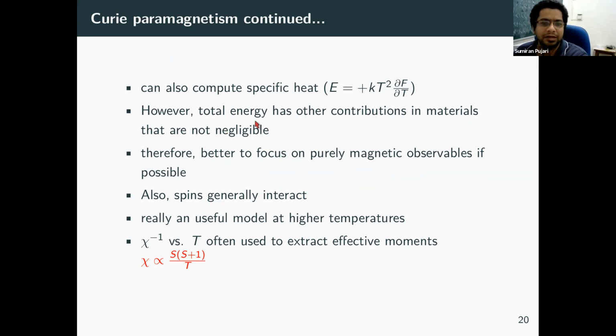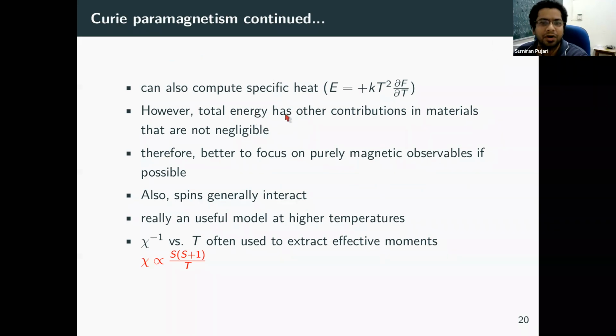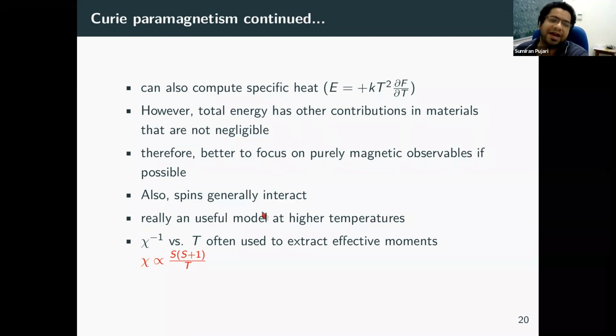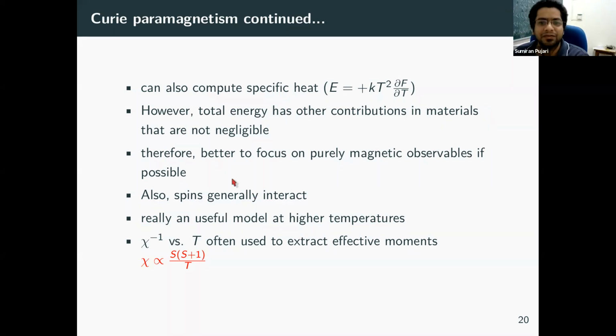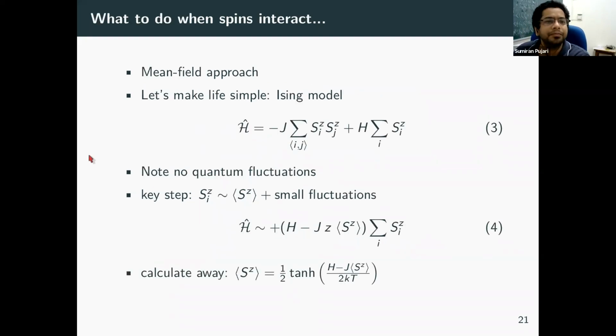But in real materials, the total energy actually has other contributions, and they cannot be neglected. Therefore, it is better to focus on purely magnetic observables like susceptibility. And also the fact remains that spins generally are not non-interacting, but they generally interact in solids. So therefore, this is really a good model at high temperatures where the thermal fluctuations and entropic effects are completely dominating, and the energetics of the spin interactions are negligible. That's when this model is a good one, and you can do some more with it, but I'll go ahead for now. So then the next question is what to do when spins interact.